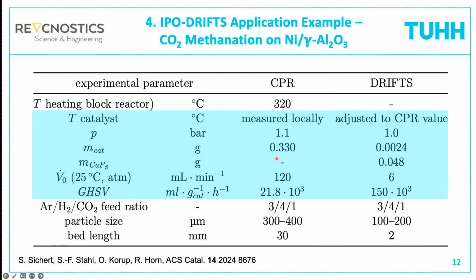And now the catalyst, we have 330 milligram of catalyst in the CPR, but only 2.4 milligram of catalyst in the DRIFT cell. So a very small amount, so that we can just measure the adsorbate signals, but we don't do a whole lot of conversion there. And to fill up the crucible in the DRIFT cell, we have added here 48 milligram of calcium fluoride as a diluent. Then we can look at the volumetric flow rates. We have 120 milliliter per minute through the CPR, which is a very typical value, and we take out 6 milliliter per minute, so 5%. It's a very small amount. It doesn't disturb the flow in the compact profile reactor a whole lot.